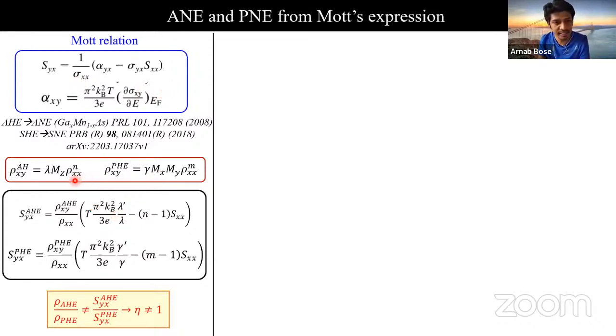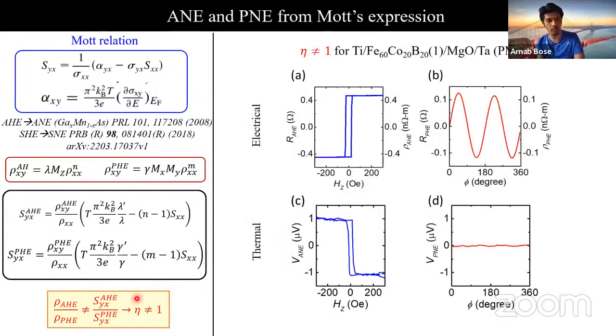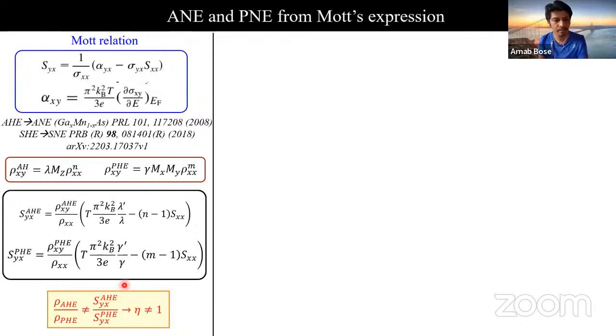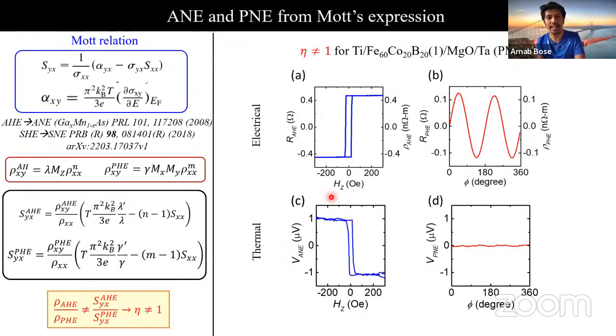So there are different factors as shown here. And if we take the ratio of them, there is no reason that for a material it must be equal to 1. So in many cases, it may not be equal to 1. Just to cross-check this, we considered what happens in a regular standard sample, such as a 1 nanometer iron, cobalt, boron perpendicular magnet. We did electrical and thermal measurements. We found both AHE and PHE in the electrical measurement, and we do observe the anomalous Nernst effect, but the planar Nernst signal was very small. It indeed implies that the value of eta could be different from 1 if we have a conducting magnet.